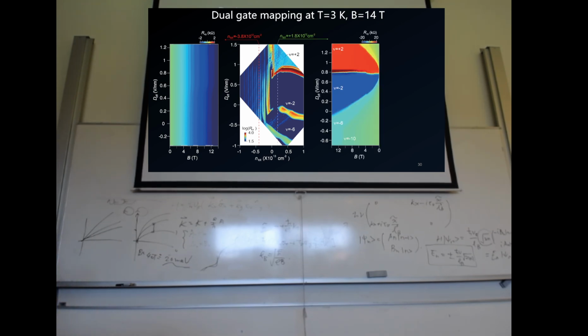But if you do the same mapping of electric field and magnetic field using this Rxy as a representation, you can see that along this green dashed line, the whole thing is changed. Instead of this conventional picture, the graphene is now behaving very strangely. It's mind-boggling, because the blue and red colors here represent two Chern numbers of +2 and -2, which are the quantized plateaus. These areas are not a cutoff of the plot. It's purely measured data, at 12 something kilo-ohms, and it extends to very low magnetic field, almost hitting the B equals 0 line. So it's almost impossible in graphene, even for the best quality graphene, to have quantization at a field of less than some Tesla.